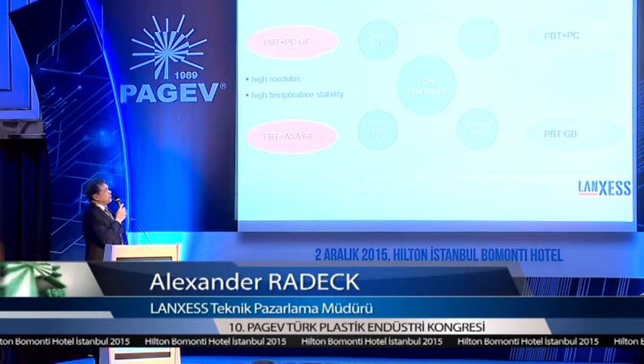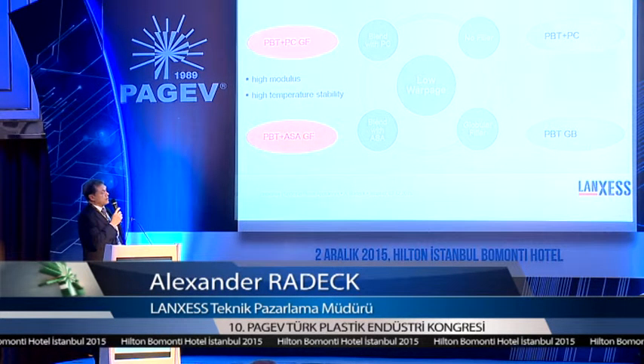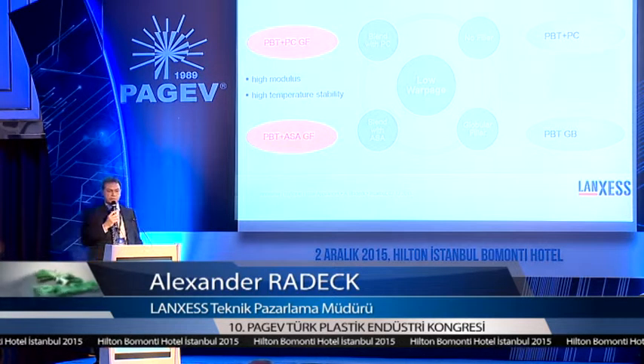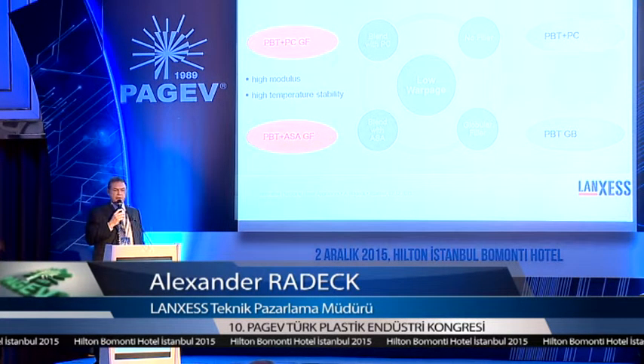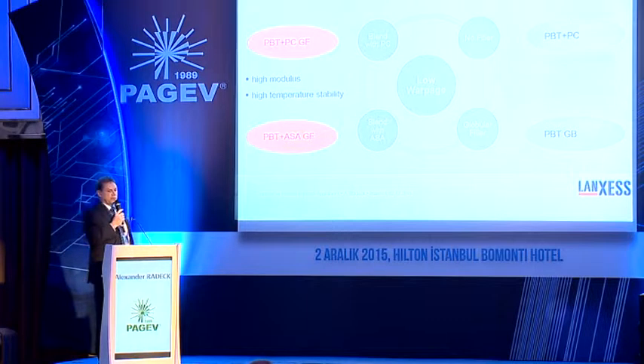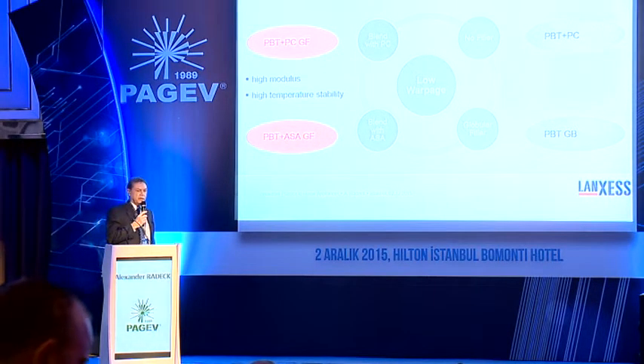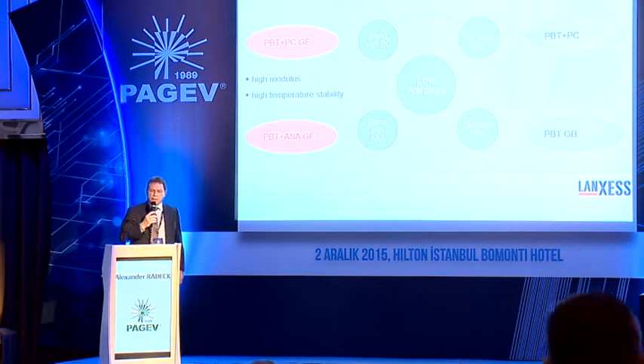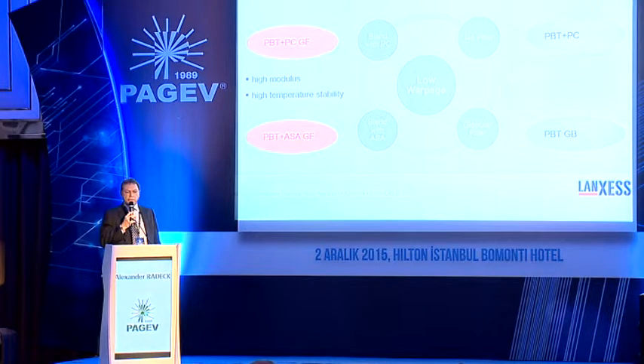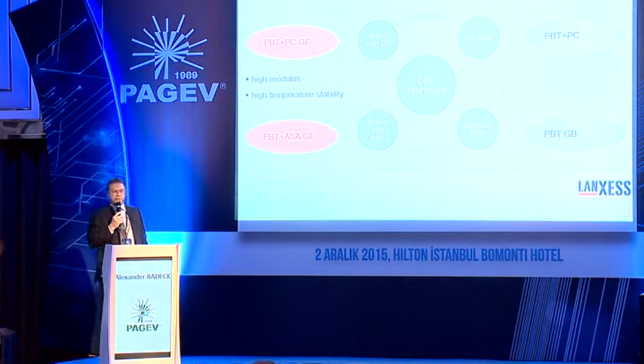How to do it when you go into PBT? PBT is always somehow related to challenges with regard to low warpage. But if we want to improve this, then usually we use blends. This can be with polycarbonate or with ASA, acrylonitrile styrene acrylate. And to have the mechanical properties, it is of course reinforced by glass fibers to achieve high modulus and also higher temperature stability.